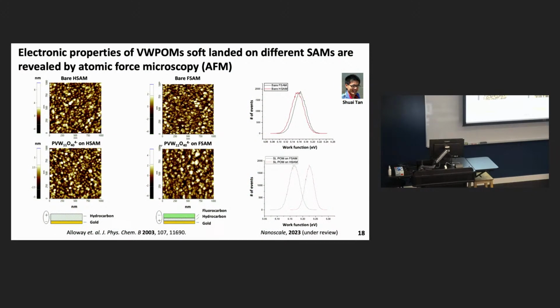So when you're working with molecular qubits, one issue, of course, is how they interact with the surface and with each other, and underlying that is their charge. So we have here some results following soft landing of these qubits onto different self-assembled monolayers that were obtained using atomic force microscopy. This is a spatially resolved technique which allows you to basically interrogate the surface with near nanometer spatial resolution. And in this case, we can actually measure the height features, and we can also measure electronic properties such as the work function, or the energy required to remove an electron from one of these deposited layers.